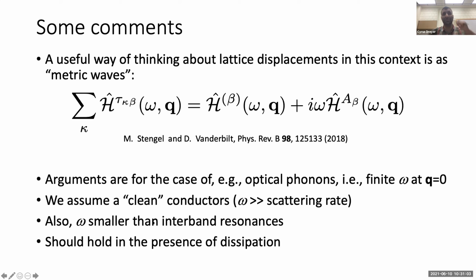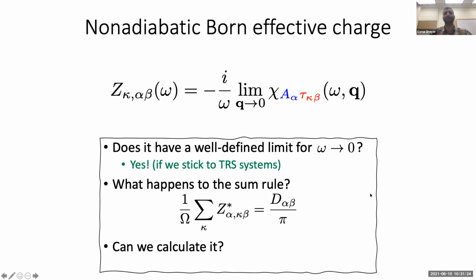Also, we're assuming that the frequencies are smaller than any interband resonances. And we think this should hold also in the presence of dissipation, though we haven't discussed this before. Of course, in any real metal, you don't have a divergence in the optical conductivity, but a peak of finite width. Okay, so that's the answer to our second question, what happens to the sum rule? We have this generalized Born effective charge sum rule, where the sublattice sum of the Born effective charges is proportional to the Drude weight.